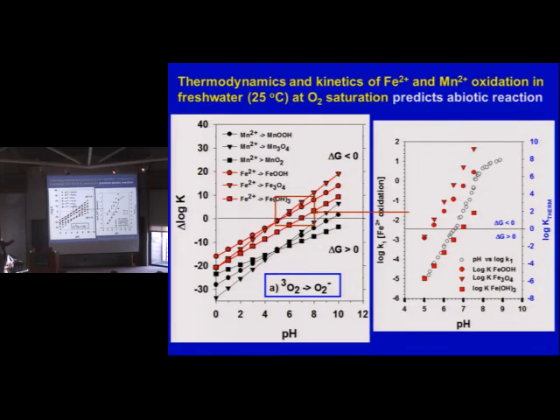Now the question is, if you get a lot of manganese in banded iron formation, does that then suggest that the pH was high? And I don't know enough about all the banded iron formations and how much manganese is in them, but most of the time it's very, very low. So if you started to get lots of manganese, I would expect that that banded iron formation might have formed at a higher pH.